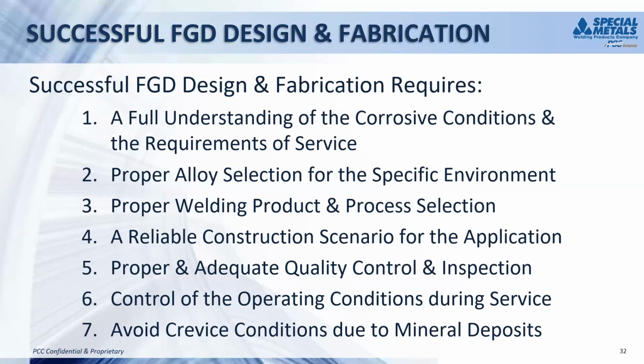And the problem of crevice corrosion, I mentioned it's probably the most aggressive type of corrosion we encounter. It takes place under mineral deposits, under deposit corrosion. So if you can operate the system so that those mineral deposits don't form. For example, the weld I showed you in the duplex steel stood proud of the base metal. Make sure the welds are not that high. If you can avoid the mineral deposits, you'll go a long way to improving the life of your system.